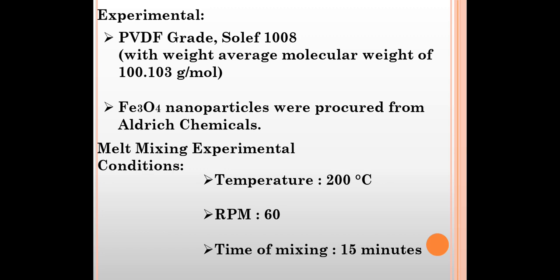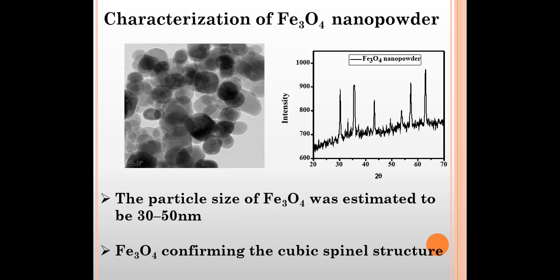The process parameters are: temperature is 200 degrees Celsius, rotation per minute is 60, and the time of mixing is 15 minutes. The characterization of Fe3O4 nanoparticles is done using SEM and XRD techniques. The SEM image clearly shows that Fe3O4 nanoparticles are uniformly distributed, having a uniform size distribution of 30 to 50 nanometers. The XRD analysis shows that Fe3O4 nanoparticle has a cubic spinel structure.